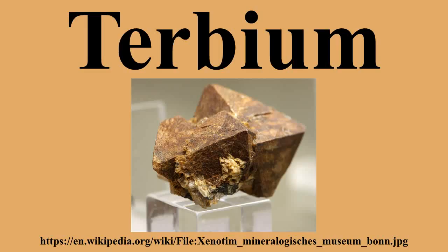Crushed terbium-containing minerals are treated with hot concentrated sulfuric acid to produce water-soluble sulfates of rare earths. The acidic filtrates are partially neutralized with caustic soda to pH 3 to 4. Thorium precipitates out of solution as hydroxide and is removed. After that, the solution is treated with ammonium oxalate to convert rare earths into their insoluble oxalates. The oxalates are converted to oxides by annealing.